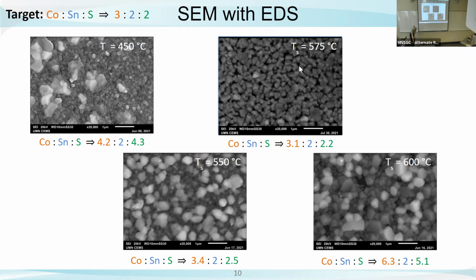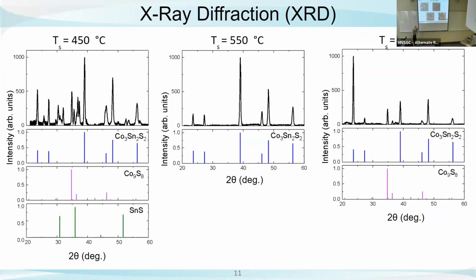And then this sample is our closest to the 3 to 2 to 2, which is good for us because now we know that that material is in this nice looking film that we want to use more of. And then as we get even hotter, you can see that our ratio actually gets worse again. So not exactly what we want, but even though we have all of the right things, we do care about the crystal structure. So we actually performed some X-ray diffraction on these samples.